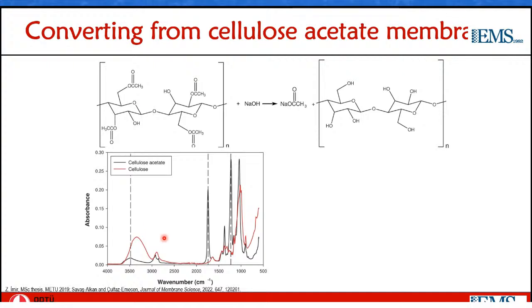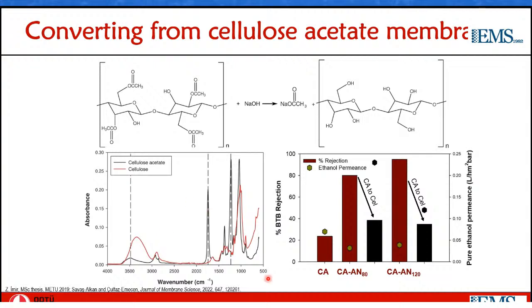And then we wanted to see if we can fabricate cellulose acetate nanofiltration membranes and then convert them into cellulose nanofiltration membranes, this time by a different way of fabrication. So we made cellulose acetate membranes by a certain recipe. And then we subjected these membranes to 2 different annealing treatments at different temperatures of 80 and 120 degrees. This is actually known to densify the cellulose acetate structure, increase rejections, and decrease permeances. And this was also what we observed. We observed increasing bromothymol blue rejections and decreasing permeance with annealing and with increasing annealing temperature. However, when we converted these cellulose acetate membranes to cellulose membranes, we observed a drop in rejection and a simultaneous increase in permeance.